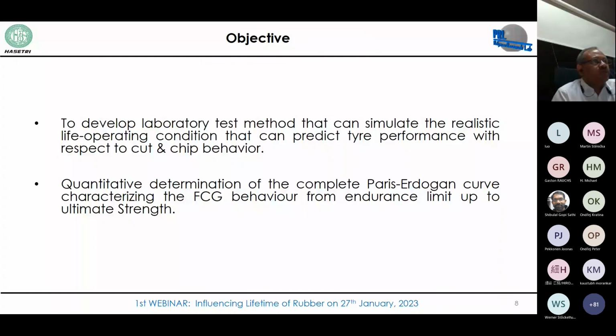So what is the objective of this particular work? To develop a laboratory test method that can simulate the realistic live operating condition and can predict performance with respect to cut & chip behavior, which is very important. At the same time, also the quantitative determination of the complete Paris-Erdogan curve characterizing the FCG behavior from endurance limit up to ultimate strength.